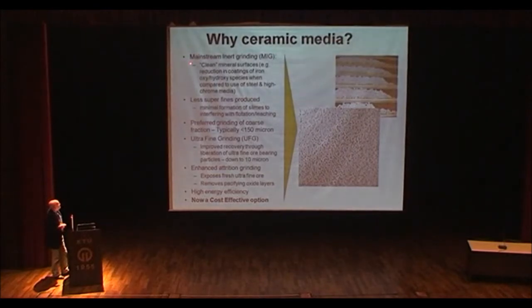But I think the big one up here is what we call mainstream inert grinding, or MIG. It was developed by the platinum mines in South Africa. And the need for that is the fact that one of the problems when you're milling the ore is that certainly on fresh sulfide faces in an aqueous environment in mills, you end up with a problem where you get a passivation of your sulfide particle from iron oxides, iron hydroxides.